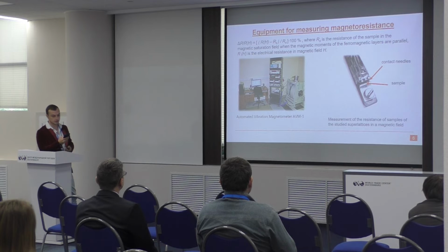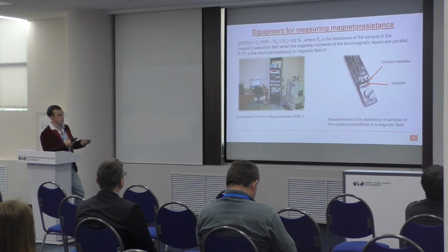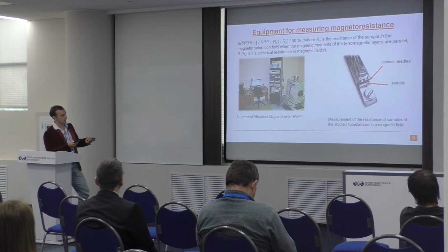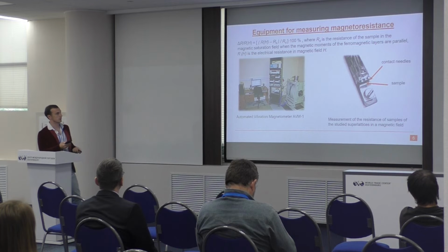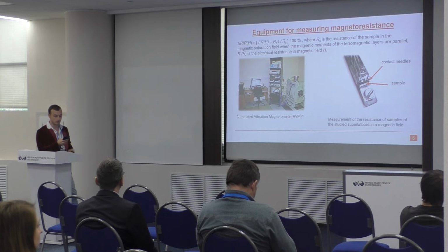The resistance of the samples of the studied superlattices in a magnetic field up to 19.5 kilooersted was measured by a four-contact method with pressure contacts. The photo of this method you can also see on the screen, where the contact needles and the sample are pointed out by an arrow. The vectors of the magnetic field strength and the current during the measurements were directed perpendicular to each other in the plane of the film layers. The measurement was carried out at room temperature.